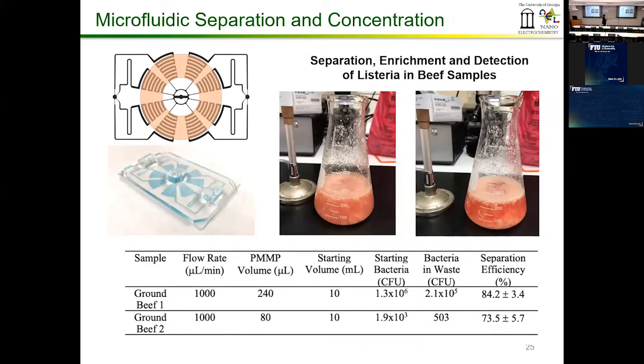So just taking one step further, instead of doing it manually, we developed a microfluidic platform where you can send the samples and you have a circular, hollow, concentric circle magnet that sits on top of this surface. And when the fluid goes inside, so you send the fluid in this port, it gets distributed, and the fluid is your contaminated food sample, liquid food sample. When it goes through the serpentine channels, the magnet is going to pull all the bacteria from the sample, and then all the liquid escapes out.